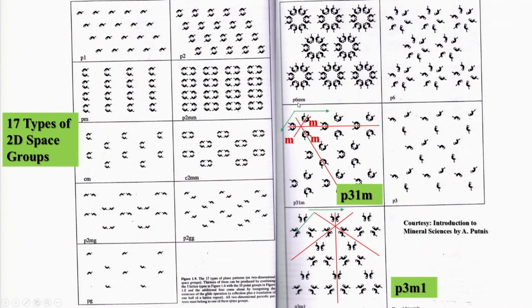and there are a total of 6 mirror planes. They occur in 2 sets, 3 in number. That is very nicely shown here by the orientation of one set of mirror planes, another set of mirror planes, these 3 you can see, and you can also think of another set of mirror planes at an angle of 30 degree between them. So, you have a very simple situation here of 6 mm, and if this is the primitive lattice here.